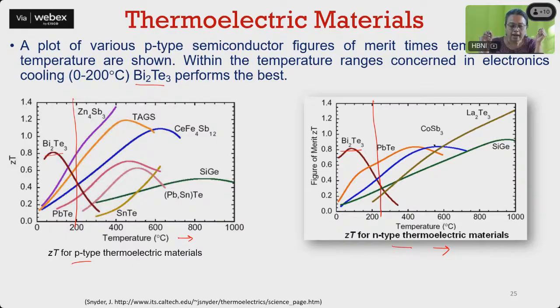So bismuth telluride is one which is performing very well at low temperature, and a lot of work is going on in that. And if you go to very high temperature, silicon germanium, SiGe, beyond 800, it can be used. In the mid temperature region, there are many different combinations. So lead telluride and TAGS. TAGS is an acronym, I will be coming to that. This is used in the 400-500 range. Much work is going on, and we are coming to a ZT of around 0.8 to 1.2 here. So these things we have to see before going into the fabrication of a thermoelectric module.